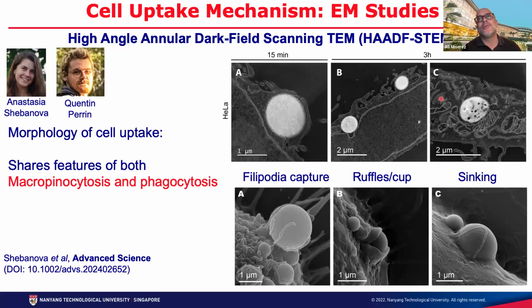Of course, the question here is, how do those strange coacervate droplets enter the cell? At first we had no idea, but by using this special scanning TEM microscopy technique, we were able to identify that those droplets are being taken up in the cell by mechanisms that share features of both macropinocytosis and phagocytosis. What you see here are cells. This is an EM-TEM section, and this is the droplet, very large here, and you can see that it's being grabbed by so-called filopodia. Those are cell structures made of actin that capture the droplet and then pull it inside the cell.